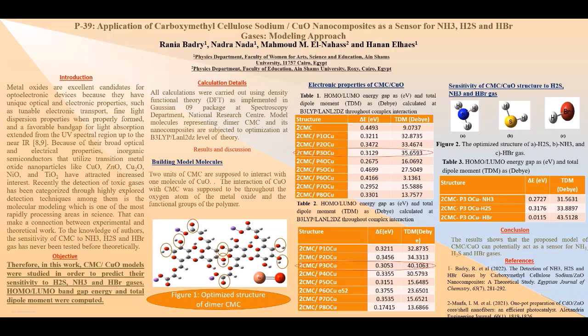To the best of our knowledge, the sensitivity of CMC to NH3, H2S, and HBr gases have never been tested before theoretically. The main objective of this study is to study the surface interaction between CMC and copper oxide and to predict the sensitivity of the proposed structure of CMC copper oxide model molecules to the different gases H2S, NH3, and HBr. All calculations were carried out using density functional theory as implemented in Gaussian 09 package at Spectroscopy Department, National Research Center.